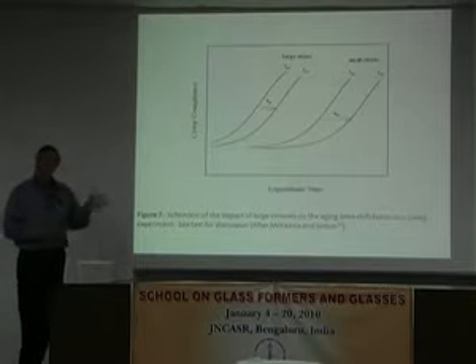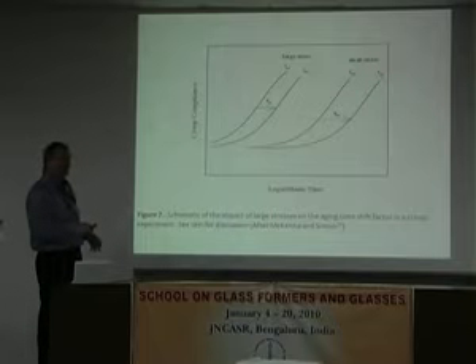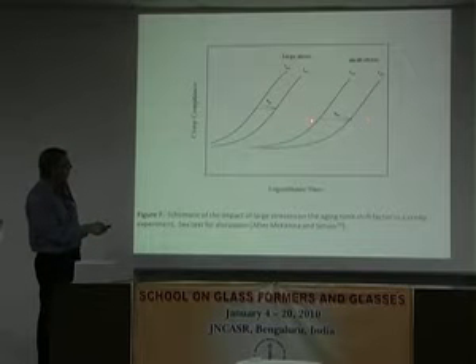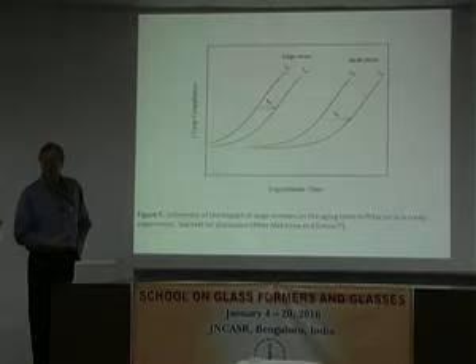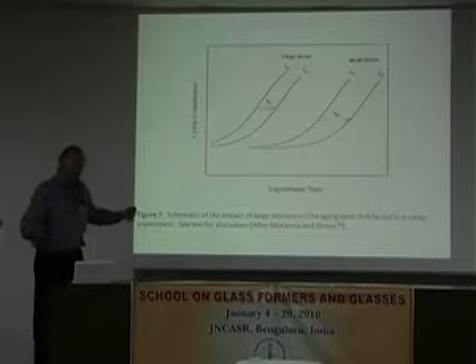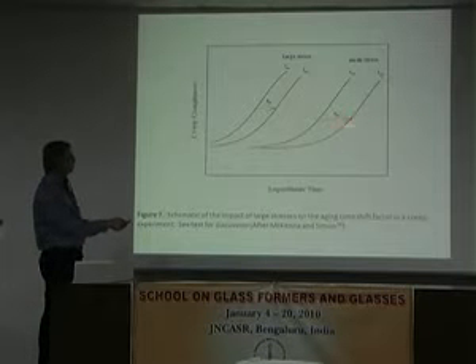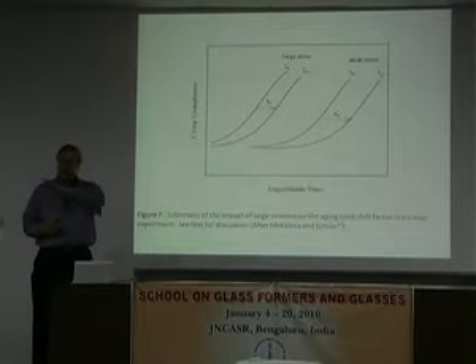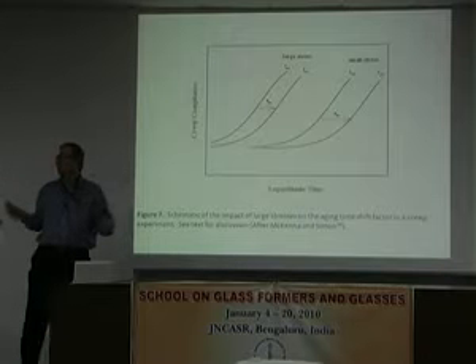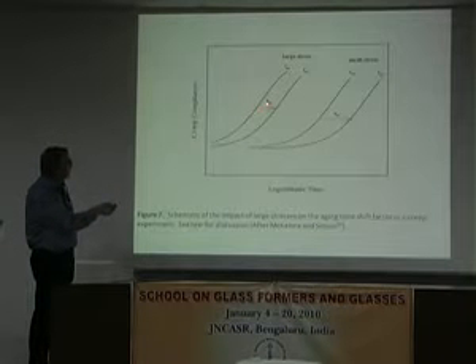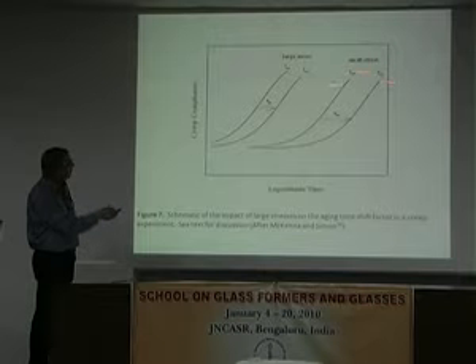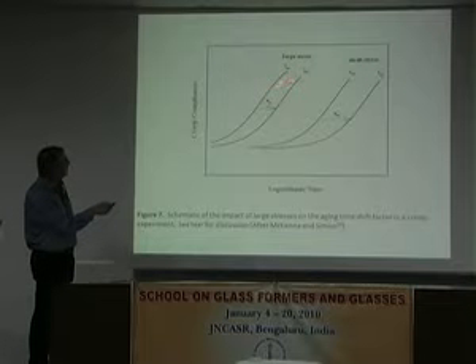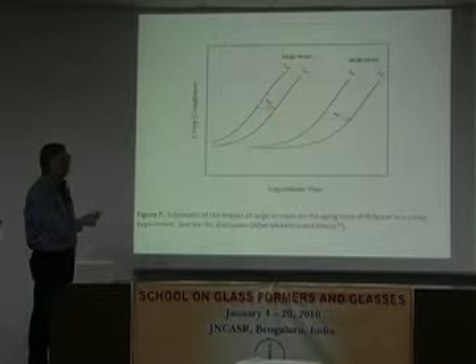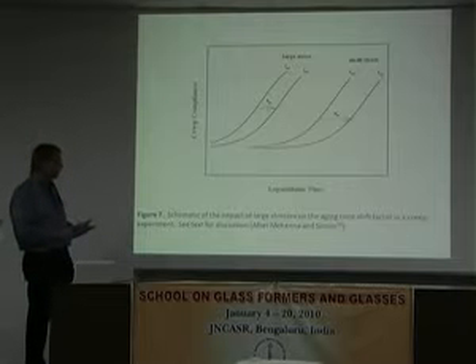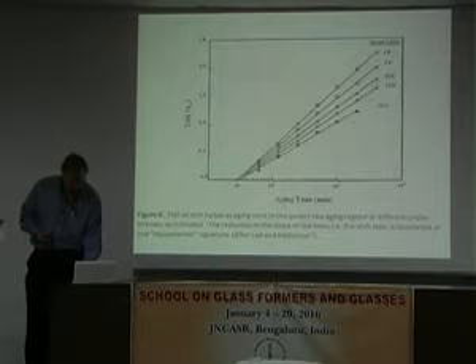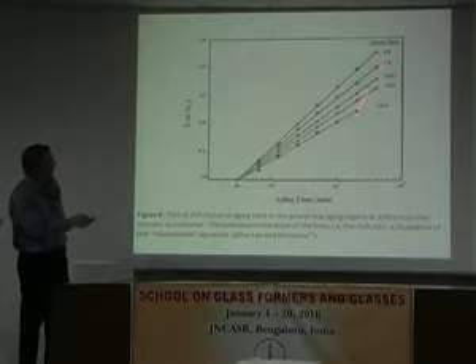So what do they mean by rejuvenation or erasure? Struik had seen that if I do experiments at small stresses, as I showed you, we get aging time superposition, and there's a shift factor that looks something like this, an aging time shift factor. He also found that when he did big stresses, he would see two things. One is that the big stress response would shift to shorter times, so you'd have a stress-induced shift to shorter times, which is consistent with an ironing type idea. But he also found that if I did, let's say, one hour and ten-hour aging times, when he did the same thing at large stresses, the shift factor was smaller. And he interpreted that to mean, well, okay, and this just shows the shift factors as a function of applied stress that we work with.